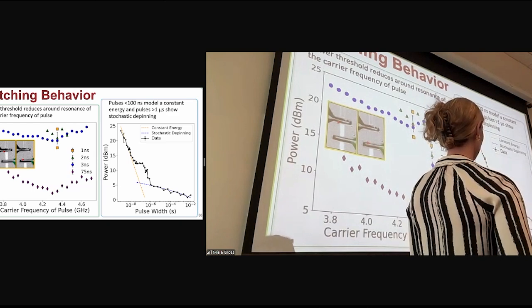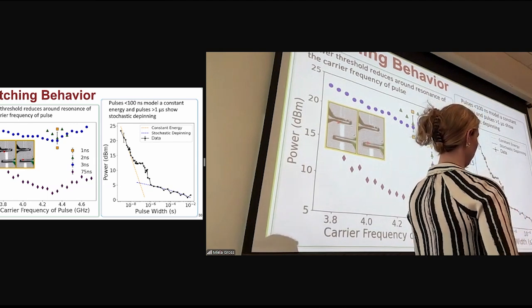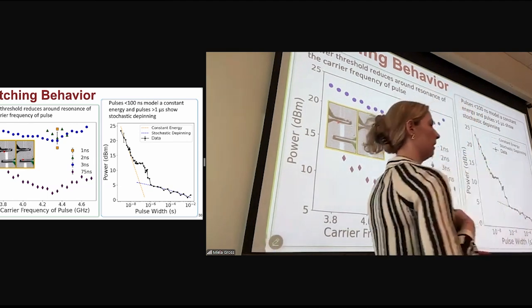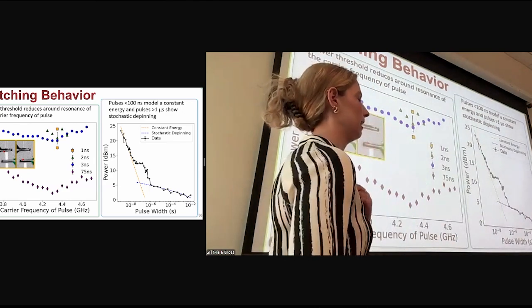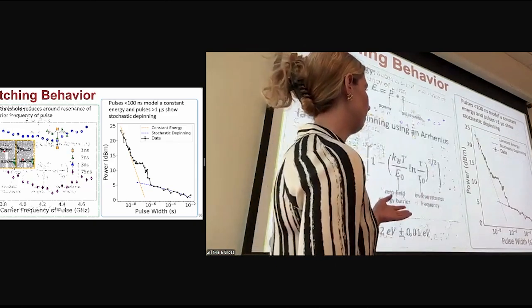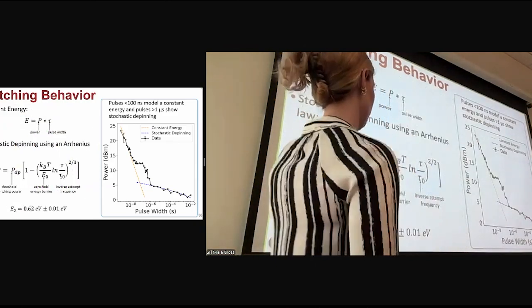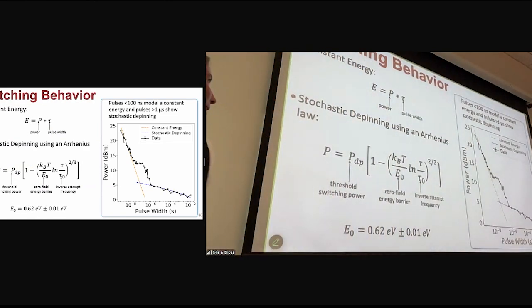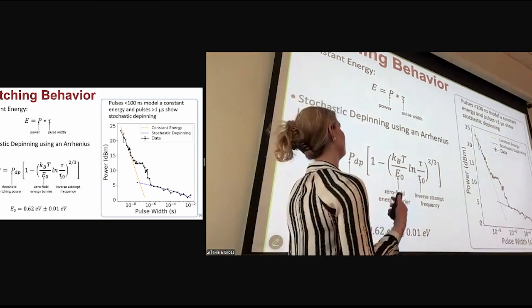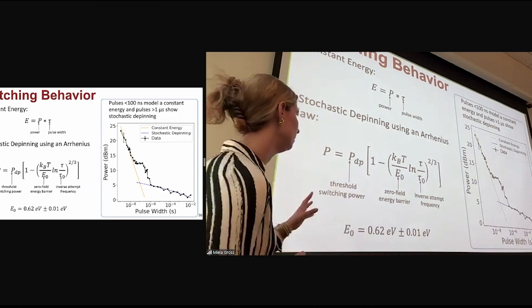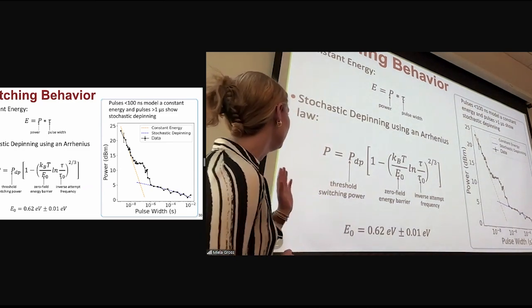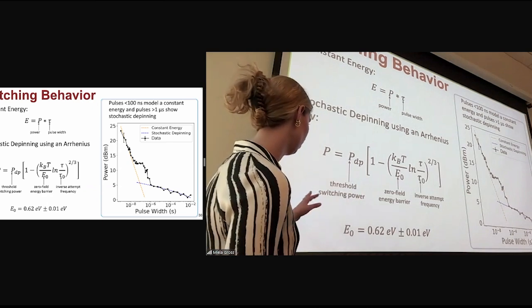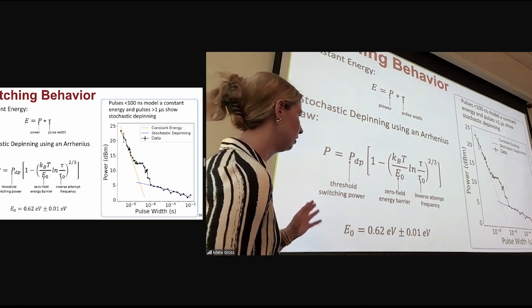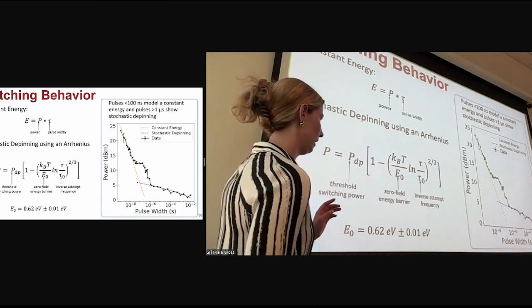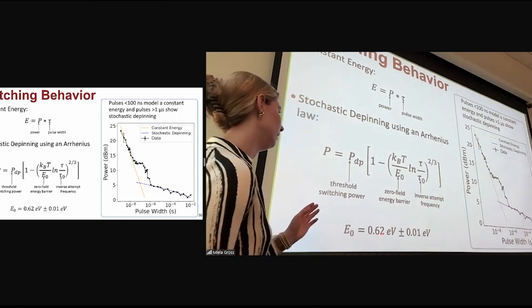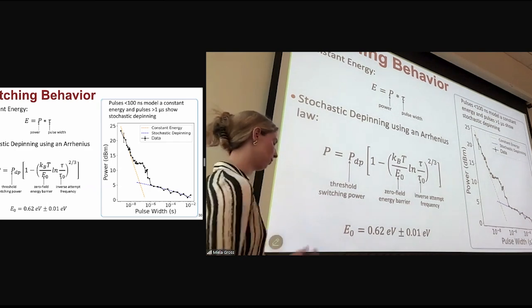On the left, we see a constant energy. Then after about a microsecond pulse and larger, we see this stochastic depinning regime, which corresponds to creep, or room temperature thermal effects affecting the domain wall depinning. The way that I fit these two regimes is with the equations here on the right. Constant energy is not groundbreaking, it's just power times time, so the power of the pulse times the pulse width. The stochastic depinning regime uses an Arrhenius law, and that involves the switching threshold power, an inverse attempt frequency, and a zero field energy barrier. We were able to fit this equation to the data on the right, and that gives a zero field energy barrier of about 0.62 electron volts.